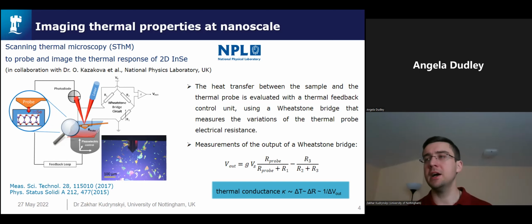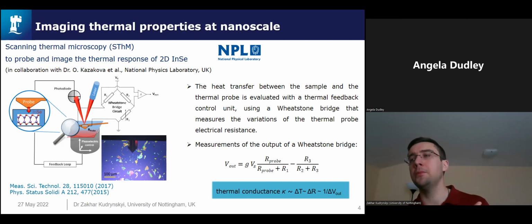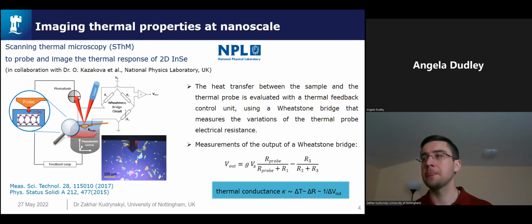The probe is a metal device which is heated by electrical current, so it gets hot. The probe is a part of a Wheatstone bridge. When this hot probe is in touch with the sample, we have heat transfer. The temperature of the probe drops, resistance decreases, and we have an unbalanced bridge. To balance it again, we need to change voltage on the bridge, and essentially we will be measuring the drop of voltage as a signature of the difference of thermal conductance of our sample. So important to know from all that is that our thermal conductance is inversely proportional to the change of output voltage on the bridge. These techniques allow studying heat transfer at the nano and micro scale.